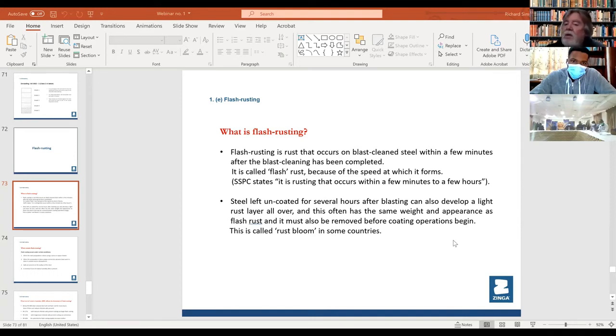If not possible, you just got to keep an eye on it. And if you see flash rusting occurring, then spray on the Zinga immediately, and then carry on with your other blasting work. But don't leave it, because you don't want to have to re-blast. Again, if you catch it at that point, it's still a light flash rust, which we call light. So there's no problem. It's when it becomes medium or heavy, then you've got to either water jet, not blast, water jet, or you've got to re-blast.